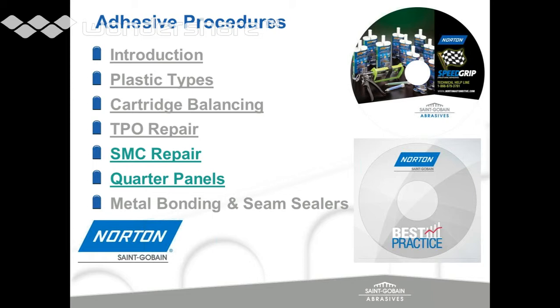It's up to them. The neat thing about the contour release film is you'll be able to tell when your repair is dry and cured. That either peels off, or the fun thing is it'll actually peel off a spreader, because most spreaders are TPO and there's no 36 to 80-grit scratch or any adhesion promoter on most spreaders out there. So there's a couple ways to tell how I know my 12 minutes is up. One, it'll peel off the spreader that you used to spread it. Two, if you use the contour release film, it'll peel back off. And three, the repair isn't hot or sticky to the touch anymore.